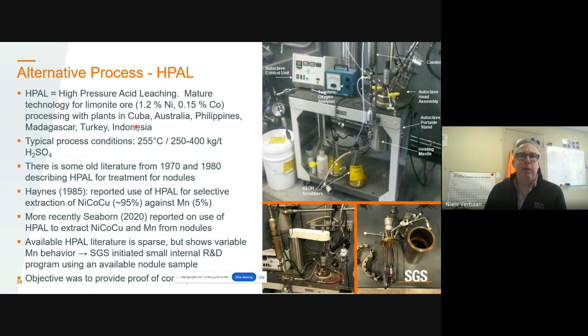Now I'll get back to the Indonesian one particularly. I think I've got a picture of one of the Philippines plants as well. Process conditions are listed here. There's a bit of old literature from the 70s and 80s on this, but it's a bit sparse, wasn't always very complete. Some have commented on selective extraction of nickel, cobalt, copper against manganese, and others have commented that there was significant manganese extraction. It wasn't quite clear. And because the literature was so sparse and showing this variable manganese behavior, we thought it would be useful to initiate a small internal R&D program using an available nodule sample.